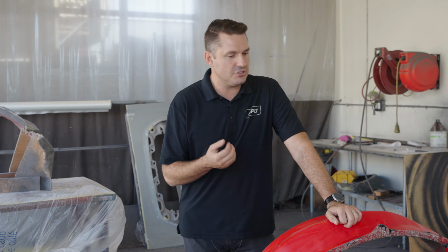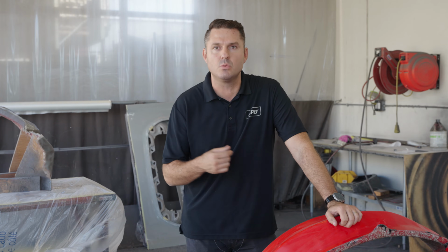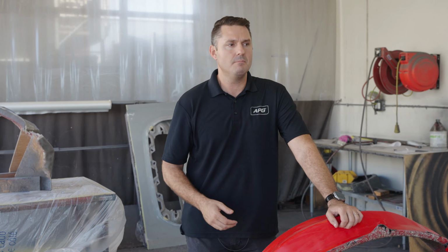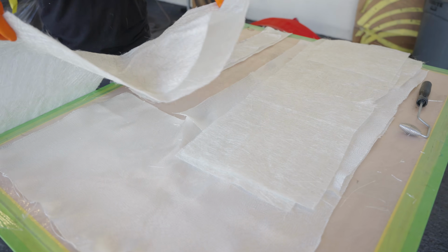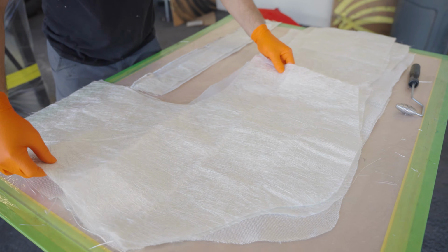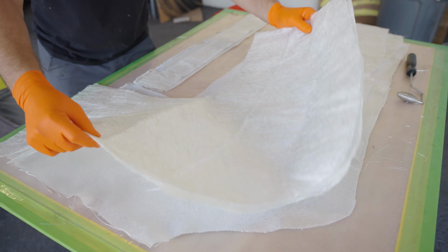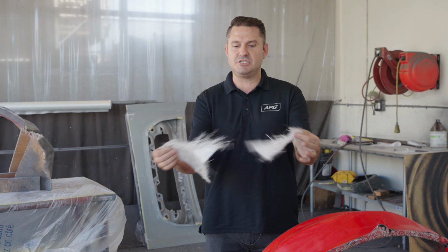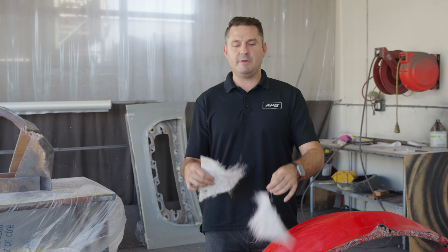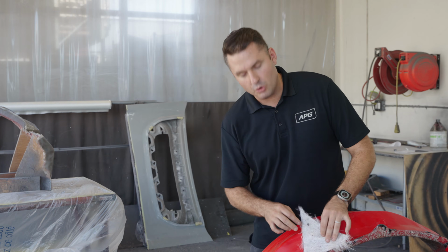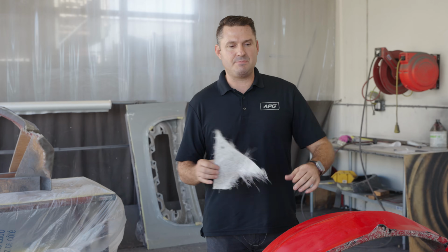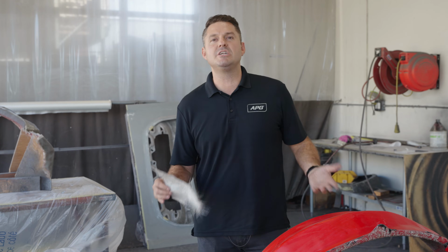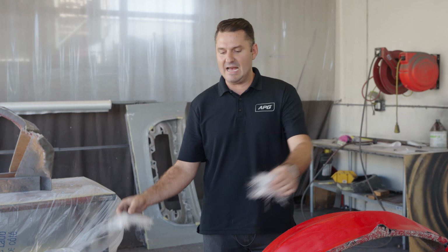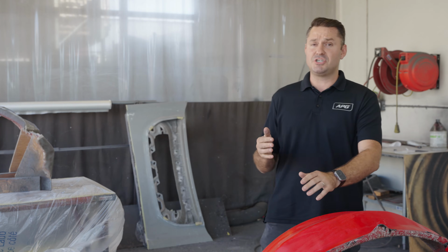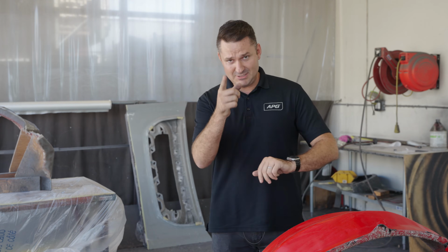And then if you're just lucky, that fiberglass manufacturer will apply a true layer of fiberglass material. Most of the fiberglass you see is a chopped strand material. A lot of fiberglass manufacturers like to work with this. This has very little tensile strength. It just tears right in half. They use this because they can tear it, shove it into corners, and it's malleable and it reduces the chance of bridging on the parts. But this stuff is weak. It has no tensile strength. I know I shouldn't have touched that with my hands without a mask, in case you guys are thinking that.